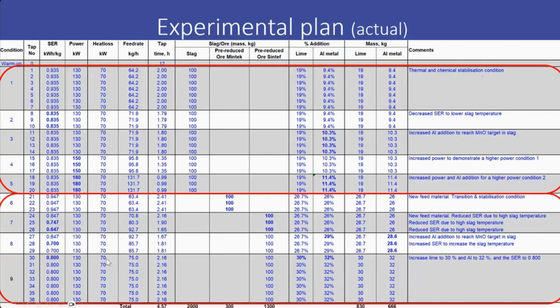Then for the second scenario of the test work, as you can see here, only 3 batches or 3 taps used MINTEK pre-reduced ore as a transition before we could use the thoroughly pre-reduced ore from Sintef. Remember I showed you the pre-reduced ore had much higher manganese content.